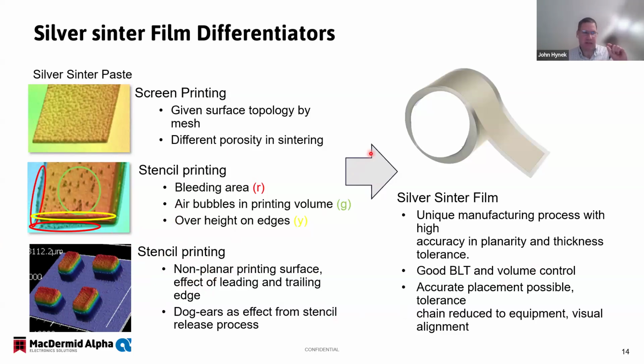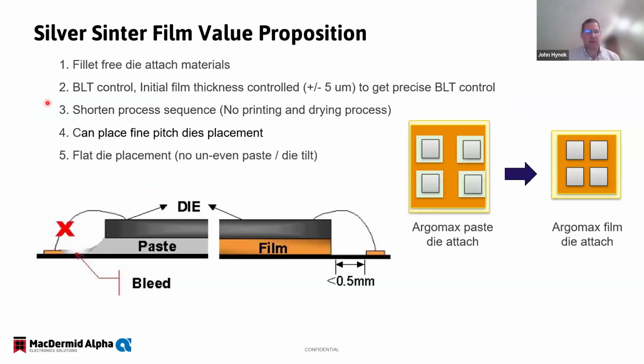When you go to a silver sinter film, the unique manufacturing process allows for a very flat surface and a very tight tolerance control of the thickness of the material. So these are concerns with paste that you don't have to worry about with film. That leads you to good bond line control and good volume control. And then you can also accurately place the materials. This gives you different advantages, which I'm going to cover in this slide here.